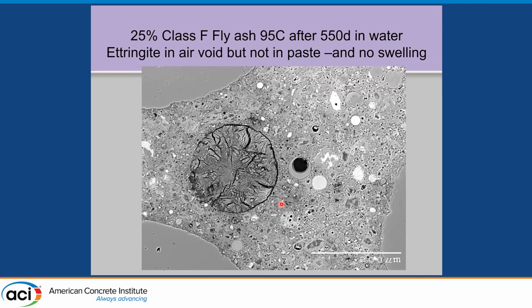And it's interesting. Here's the 25% Class F fly ash, cured at 95 and then stored in water for a year and a half here. There's ettringite filling an air void here. You can see the fly ash particles residual. There's no cracking in the matrix and there's no gaps around the aggregate. So ettringite has formed, or secondary ettringite has formed, but it's filled in the air voids in open spaces and hasn't caused damage.